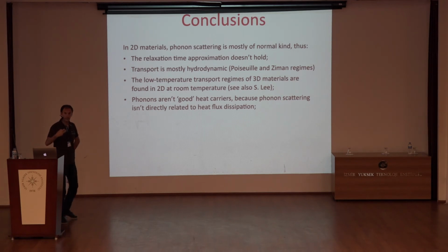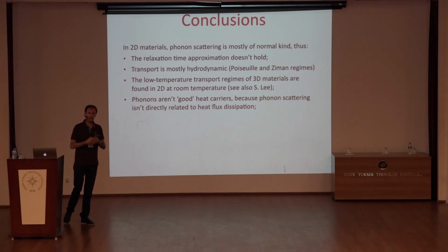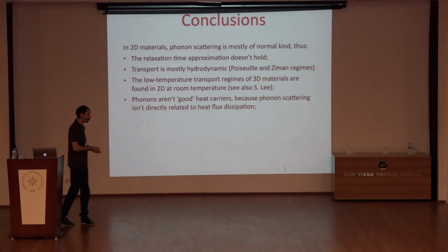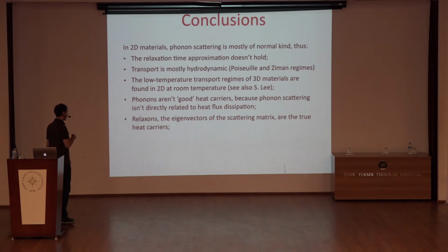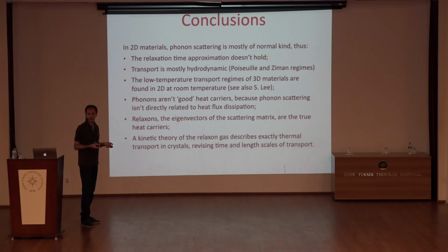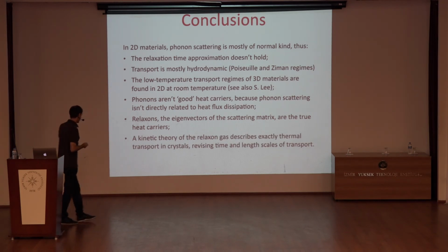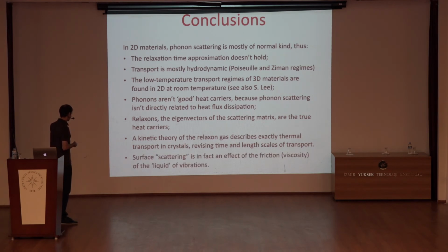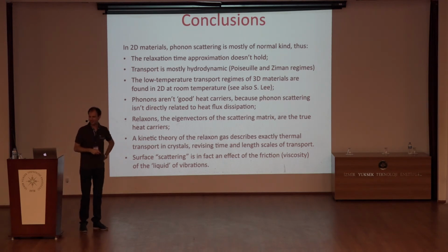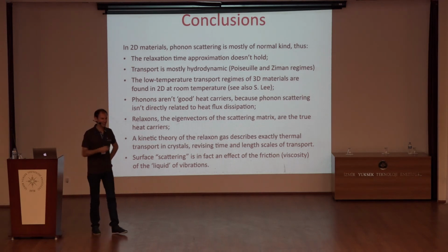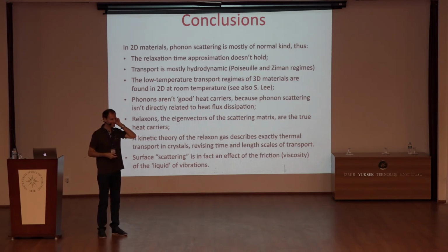And since you have this disconnection between how the heat flux is dissipated and the phonon scattering dynamics, we are also proposing to stop looking at phonons as the heat carriers and instead introduce these eigenvectors of the scattering matrix, so relaxons, which can describe the thermal conductivity in terms of the kinetic gas theory out of this gas of relaxons. And you can ask me about the last point later. Okay, so thanks for your attention and thanks for the very constructive questions.